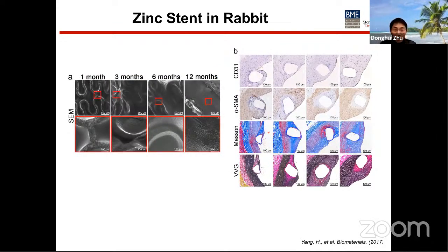This is SEM imaging showing the endothelium formation on the material surface. After 1 month, the endothelium layer is already pretty good, with a confirmed monolayer formed, showing elongated endothelium cells nicely covering the stent strut after 6 and 12 months.